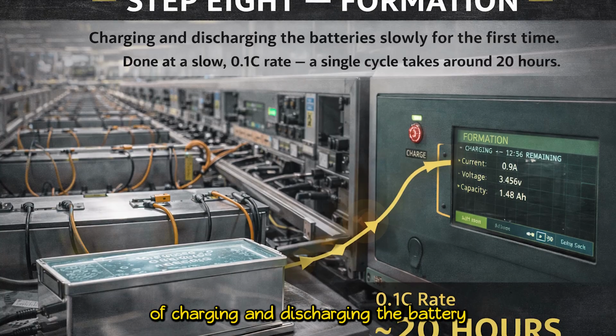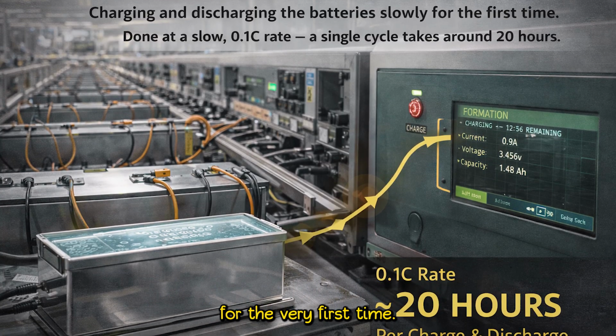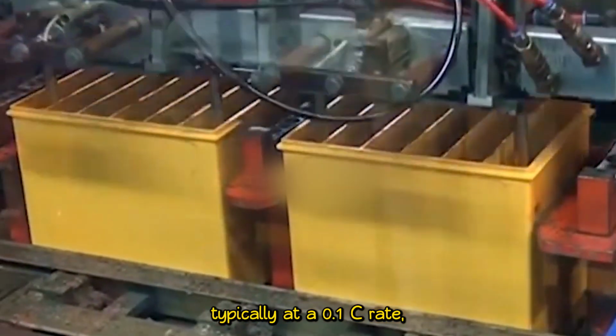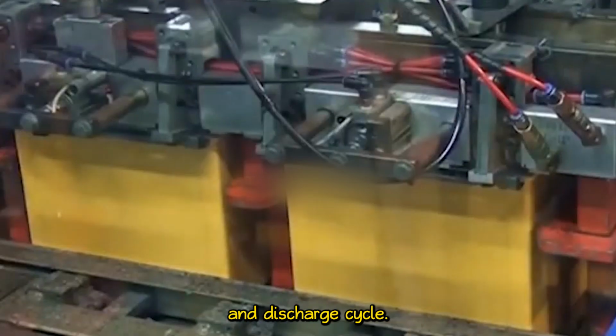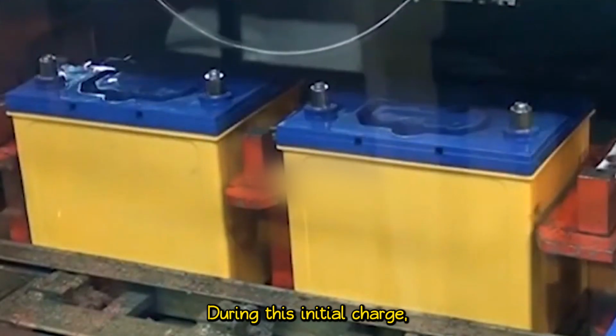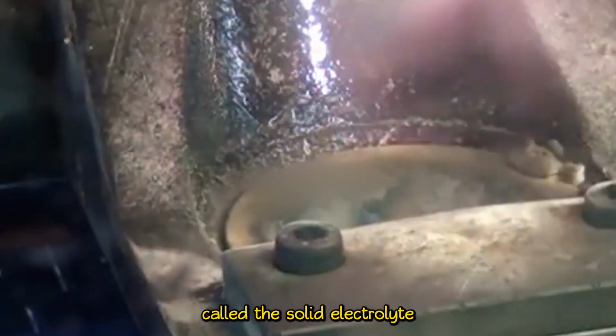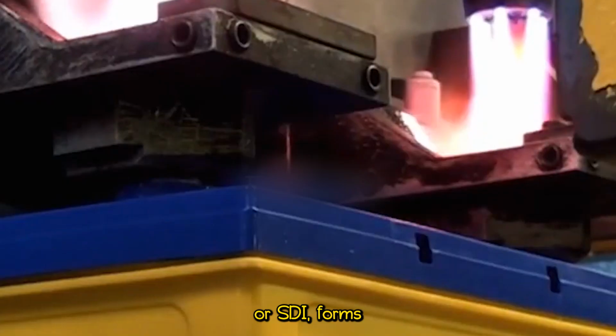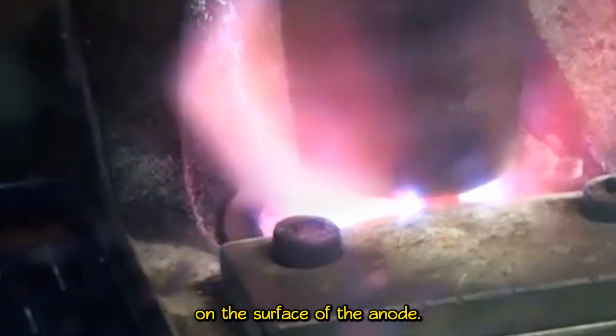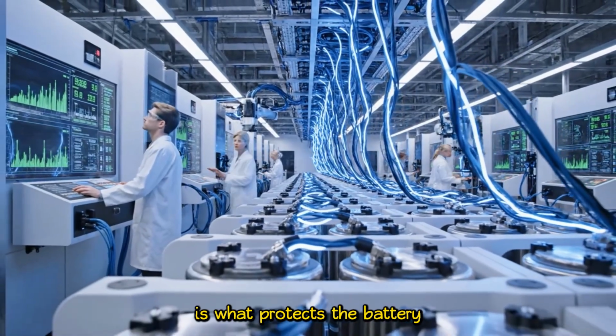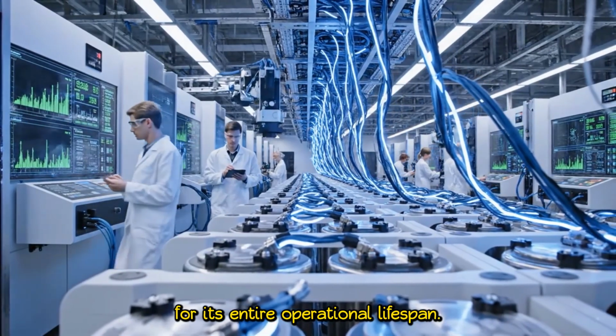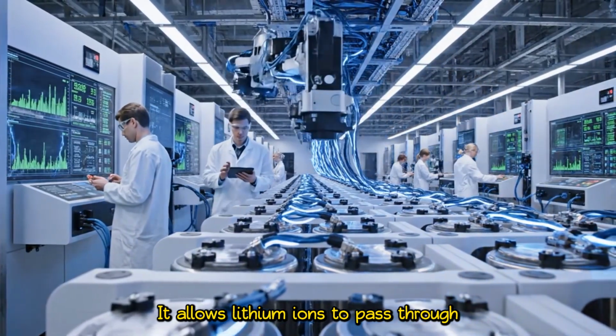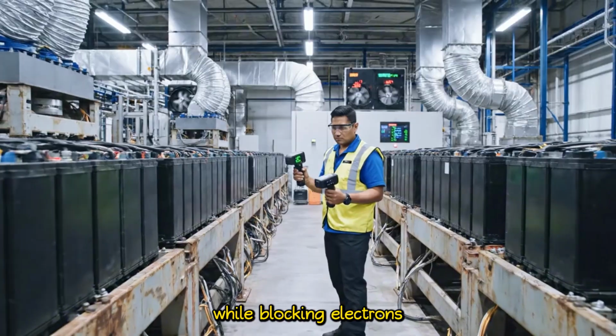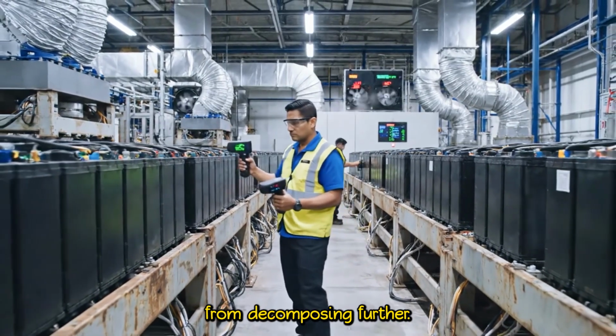Formation is the process of charging and discharging the battery for the very first time. It's done at an agonizingly slow rate, typically at a 0.1 C rate, meaning it takes around 20 hours just for a single charge and discharge cycle. During this initial charge, a critical protective layer called the Solid Electrolyte Interface, or SEI, forms on the surface of the anode. This ultra-thin layer is what protects the battery for its entire operational lifespan. It allows lithium ions to pass through while blocking electrons, preventing the electrolyte from decomposing further.